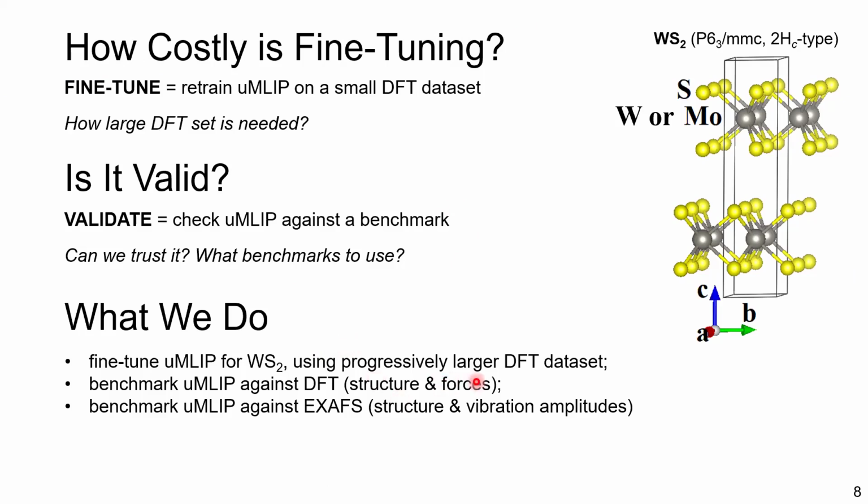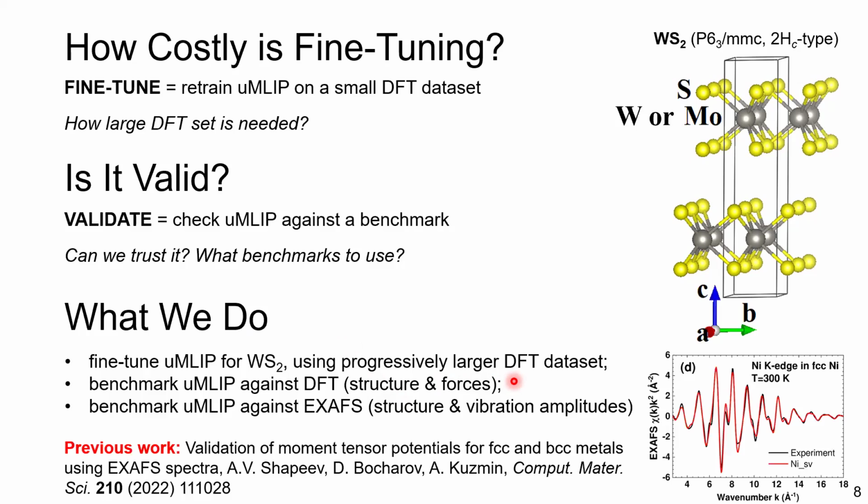And we benchmark against both DFT, which is like structure and forces, and we also benchmark against experimental data, which in this case is EXAFS, X-ray absorption spectroscopy, which is very sensitive to the structure and also very sensitive to vibration amplitudes, which makes it very suitable to test as a force field.